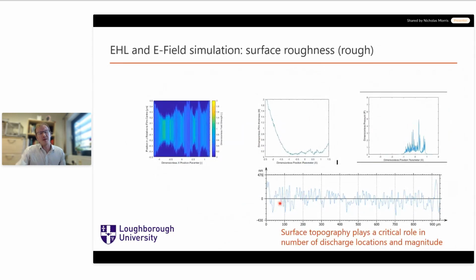Then we measured the surface roughness from an electrically damaged surface. So this was run on the test rig. We took apart the bearing, we measured it on the white light interferometer, and then we imported that line scan roughness into the model. So it's not exactly the same conditions, but it's a comparative representation of what happens. And so this scale now, instead of being to 1, this is now to 2. So anything which appears yellow on this figure is having about 1.5 to 2 times the electrical field strength of